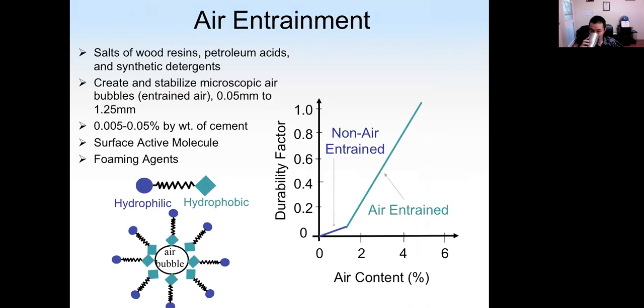So air entraining agent is typically made from organic matter such as salts of wood resins, petroleum acid, and so on. That will create and stabilize small so-called microscopic air bubbles. They can also stay in concrete for a long time. The dosage is very low, 0.005 to 0.05% by weight of cement. So it is a very, very small amount compared to fly ash and other mineral admixtures.